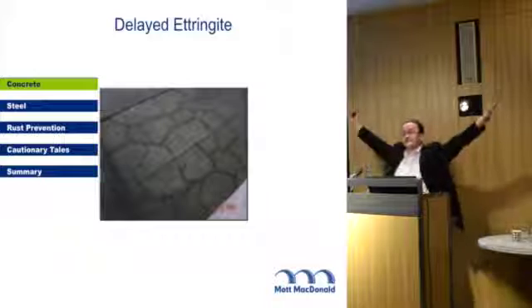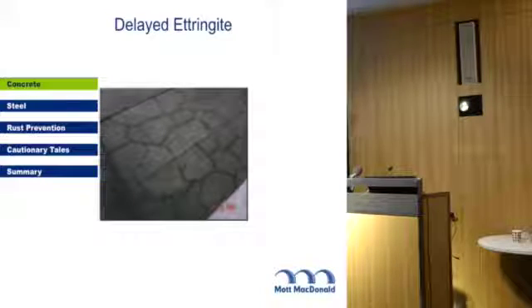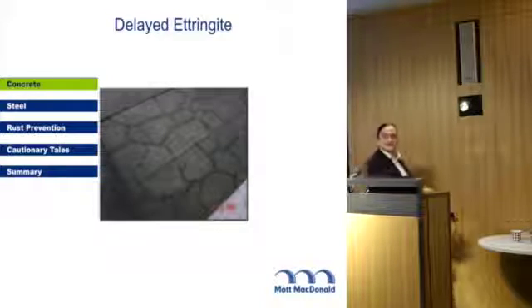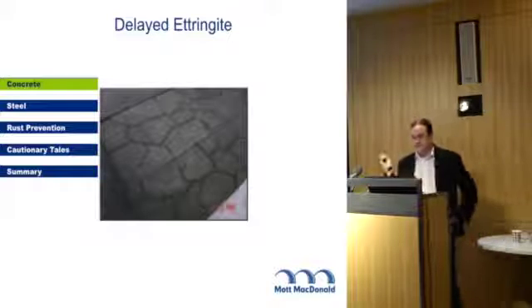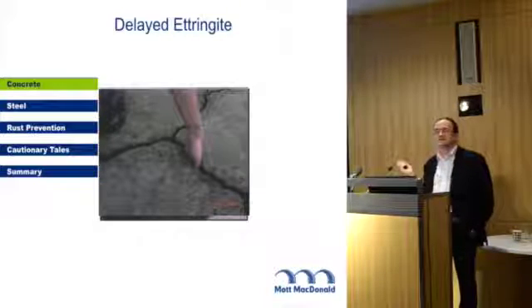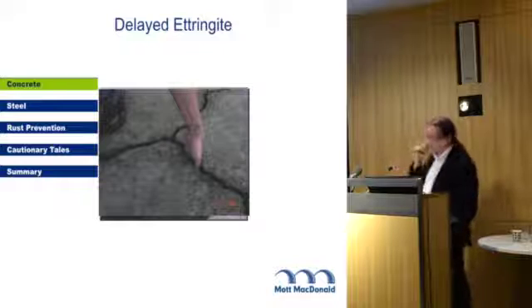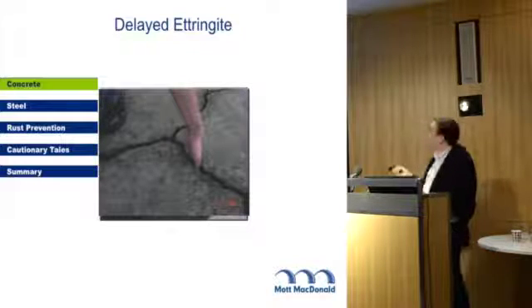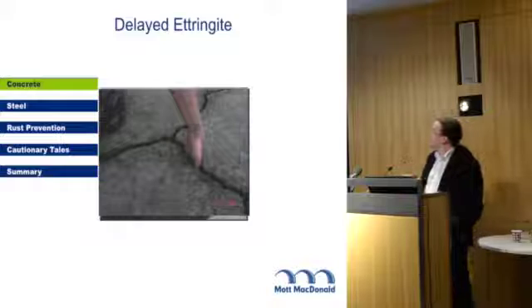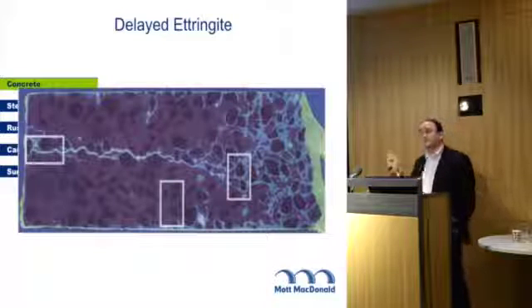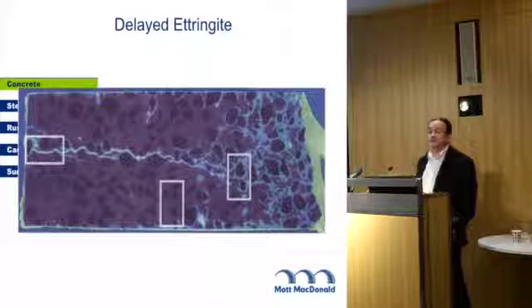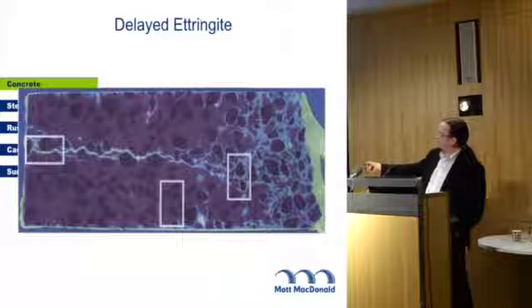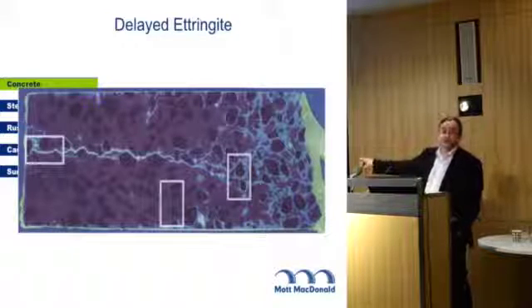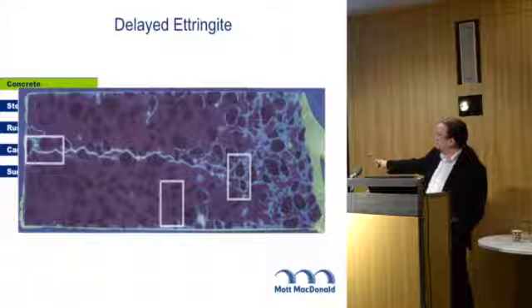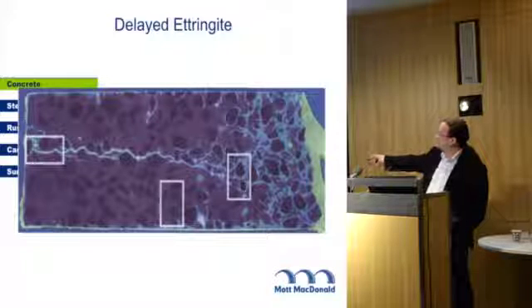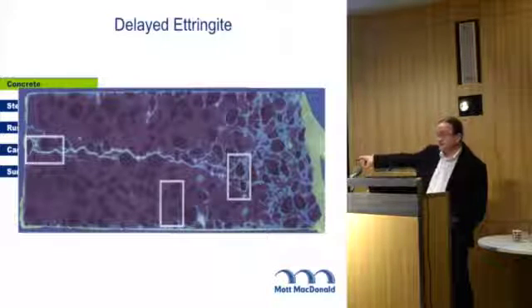And rather than looking 3-legged like ASR, they look a bit 4-legged. Again, if they're restrained, it looks kind of slightly different. The cracks can be quite large. This is passing the finger in the hole test, which is a common one used by engineers on site. But again, we can take a lump of it, send it off to a geologist, they get awfully excited, draw squares round blue things. That's basically concrete dyed blue to show up the problem. And you've got a load of this delayed Ettringite formation at depth, and then as it gets to the surface, it appears as a big crack.